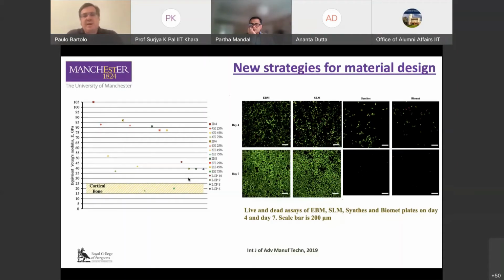The material was Ti-6Al-4V, and then we performed an extensive characterization of the plates, including in vitro biological characterization, and we compared the performance of our plates with commercially available plates like Synthes from DePuy or Biomet. We observed that our plates, without any post-processing after being printed, promote a faster interface with the surrounding tissues, as we observe from the very fast cell proliferation on top of our plates. We are preparing a project aiming to assess these plates in vivo, to confirm these preliminary results, which were very promising.